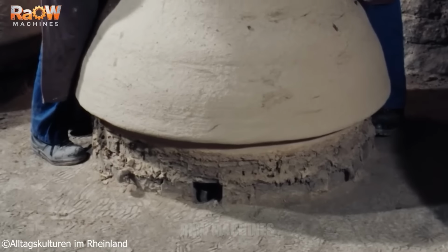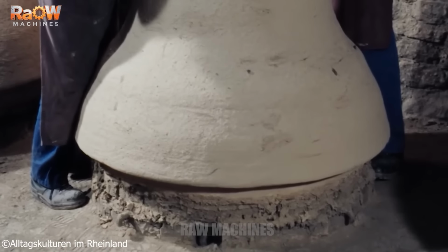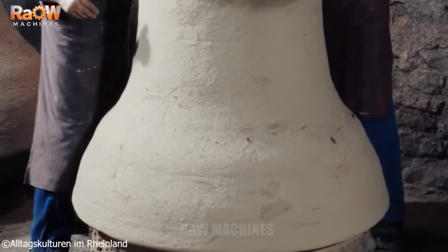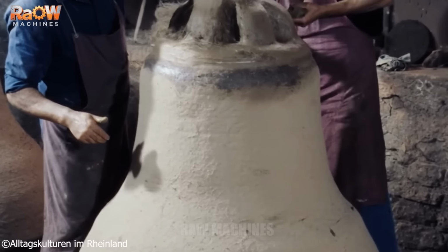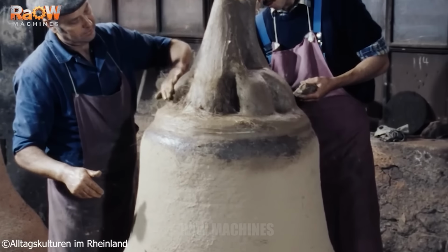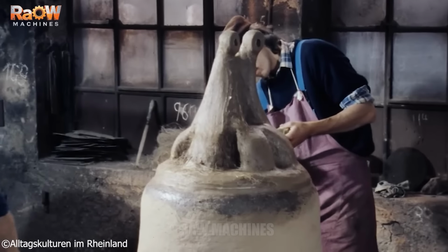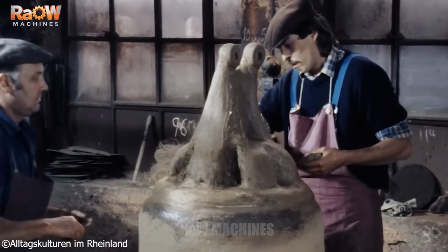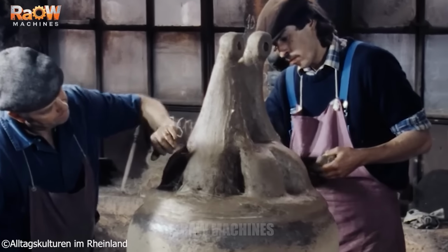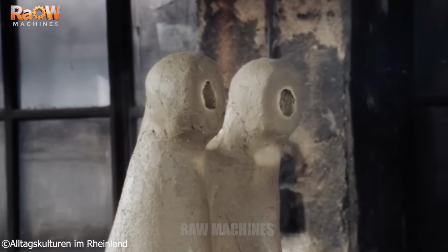After mold assembly is finished, fire is kept burning inside the core so that the mold continues to dry over the following days. Once the crown has dried, it is removed to repair cracks, trim excess jute fibers, and apply graphite to reduce metal adhesion. The upper section of the mold is coated with grease as a release agent.